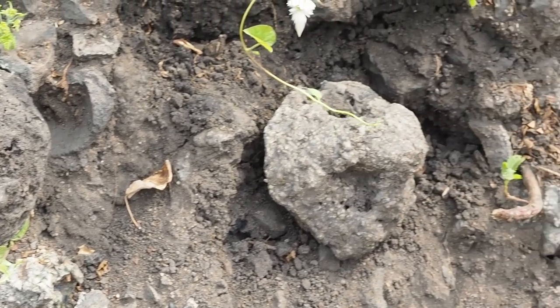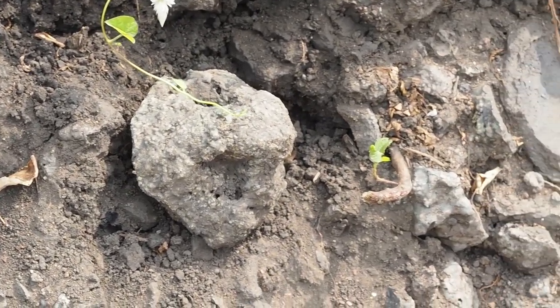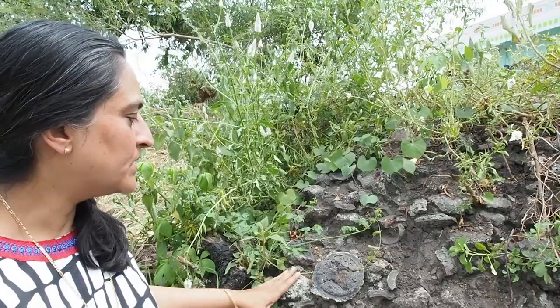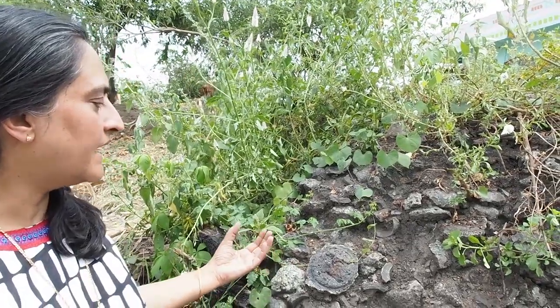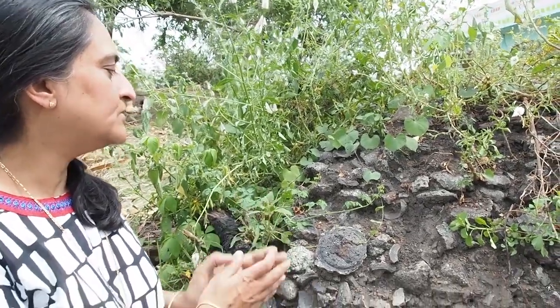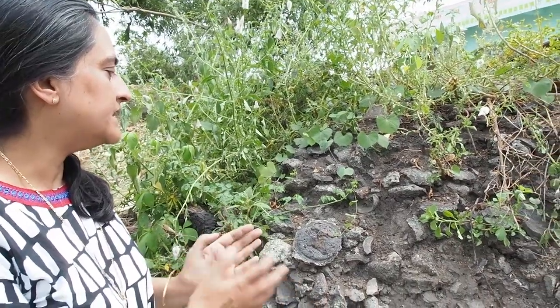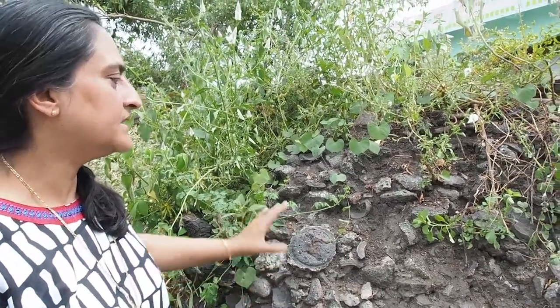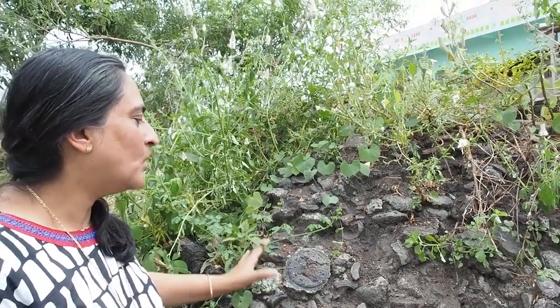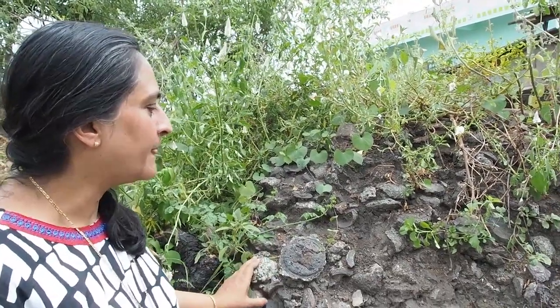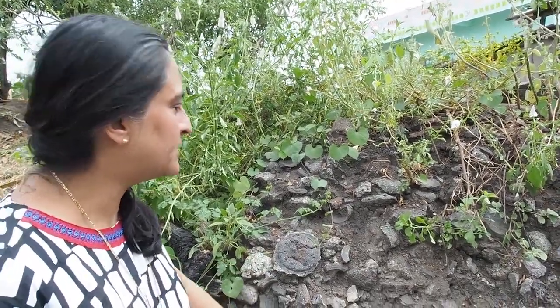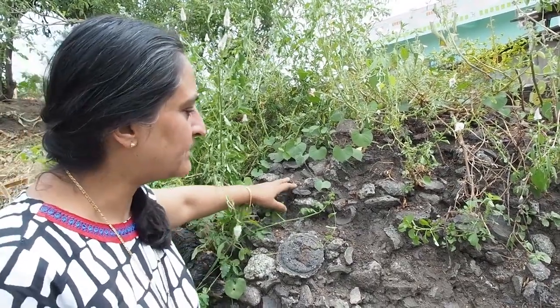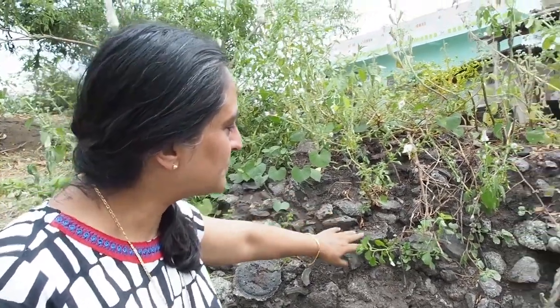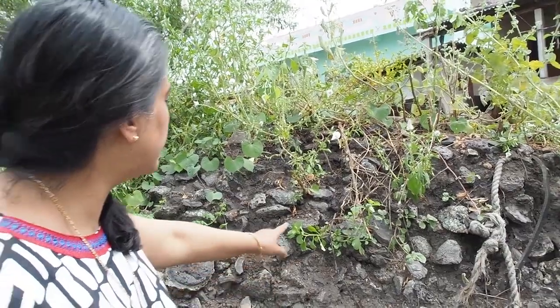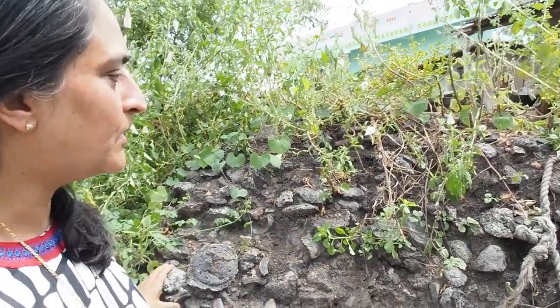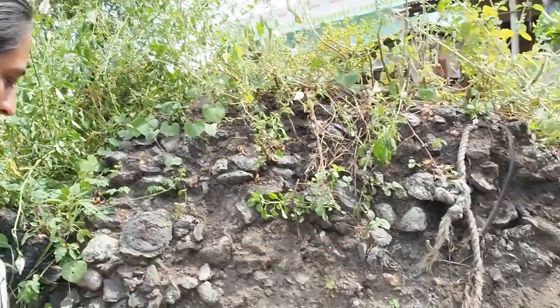Although the process that seems to have been used more widely here in the Telangana region was one where the cast iron was added to wrought iron to get a steel of intermediate composition, that is a high carbon steel of about 1.5 or so percent carbon. And so all of these crucibles relate to relics of the crucible steel production. You see the bottoms of crucibles sometimes. This seems to be the lid, this seems to be the bottom.